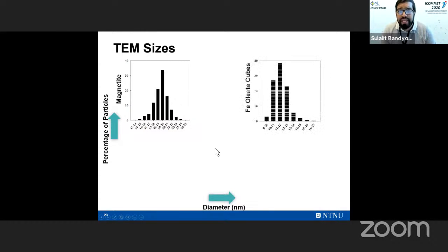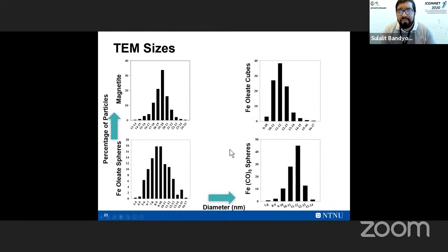The size distributions here vary between 10 nanometers to around 17 nanometers. So we cannot get big particles. If there is a requirement for bigger particles, these methods are not that good.